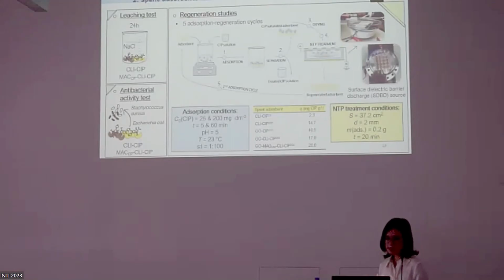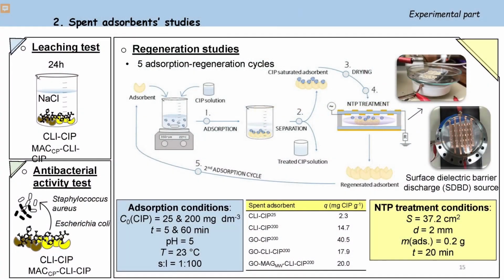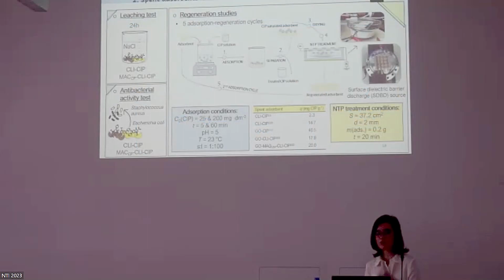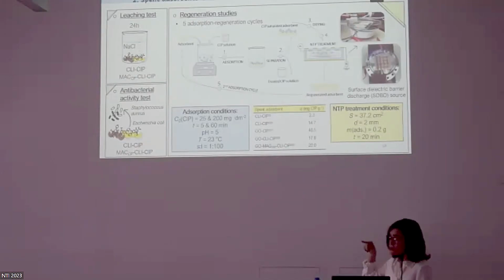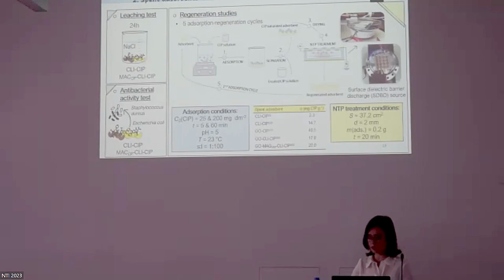So after the leaching experiment and antibacterial test towards 2 different bacterial strains, the regeneration study was performed, as I already told, by non-thermal plasma operating at atmospheric pressure. The source was surface dielectric barrier discharge. So the saturated adsorbents with ciprofloxacin after the adsorption were exposed to plasma for 20 minutes and then used again in the repeated adsorption cycle under the same conditions as before to evaluate the regeneration efficiency. So the efficiency was tested through 5 adsorption-regeneration cycles, and the table in the middle gives the spent adsorbents that were regenerated and the ciprofloxacin loading amount on them after the first adsorption cycle.